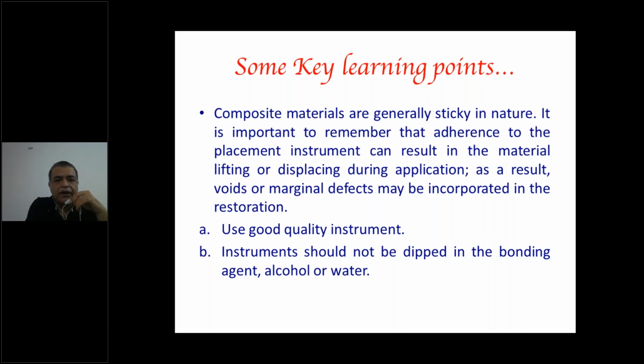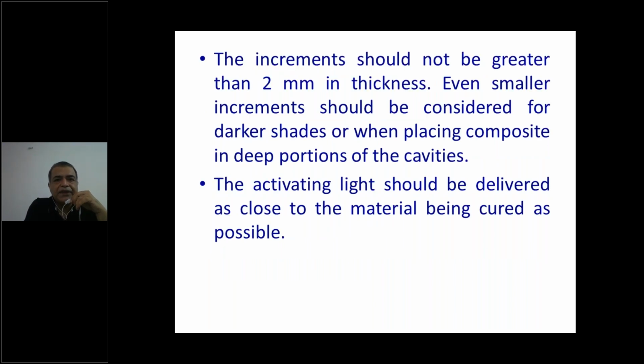So always use a good quality instrument, and I've seen this practice by some journal and older practitioners. They tend to dip their instruments in either bonding agent, alcohol, or water after every increment. Please, you don't need to do that. An increment should not be more than 2 millimeters in thickness. And when you have darker shades, they actually cure less than the lighter shades. So you can either consider increasing the curing time or reducing the thickness of composite which is placed inside the cavity. Keep the activating light as near to the material as possible.